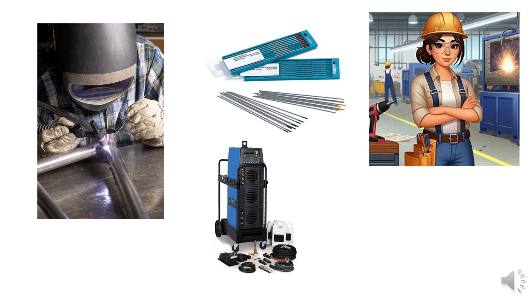Shielding gas: The shielding gas for GTAW can be argon, helium, or a mixture of argon and helium. Argon is by far the most popular. Compared to helium, argon has greater cleaning action and provides a more stable arc. Argon is heavier than air, creating a layer over the weld that protects it from contaminants. Helium, being lighter than air, requires a higher gas flow rate than argon, making it more expensive. However, as a shielding gas, helium allows for greater penetration and faster welding speeds because the arc is hotter in a helium atmosphere than in argon. The opposite is true for GMAW, so a mixture of argon and helium is sometimes used when welding metals requiring higher heat input. For most GTAW operations, pure argon is used.